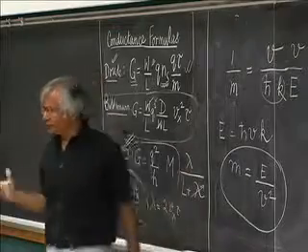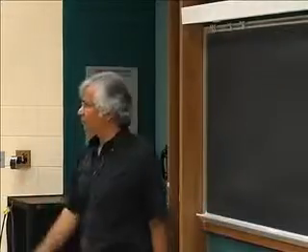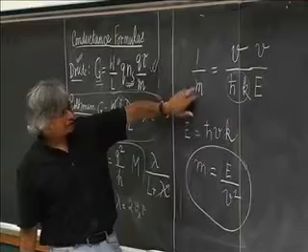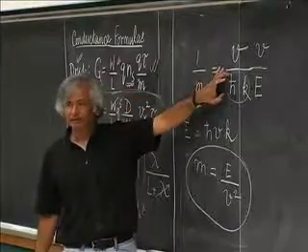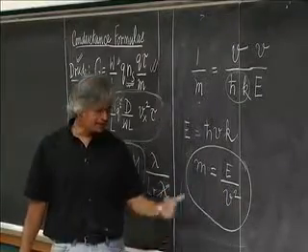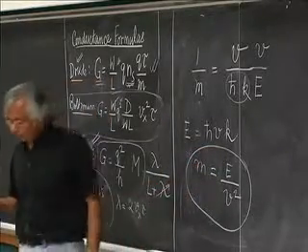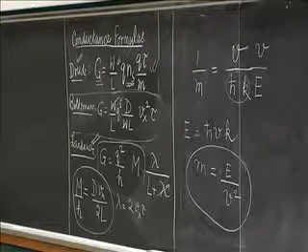Now, if you had applied this to a parabolic dispersion law, you would have got just the standard mass. It would be energy independent, there would be no problem. But when you apply it to a linear thing, if you use this relation where mass is velocity over momentum, 1 over m is v over momentum, this is the expression you get, which kind of reminds you of E equals mc square, of course. And this is also the mass that people measured in cyclotron resonance experiments. Though why that's so requires some discussion. I won't go into it now. But this is the mass they measure.